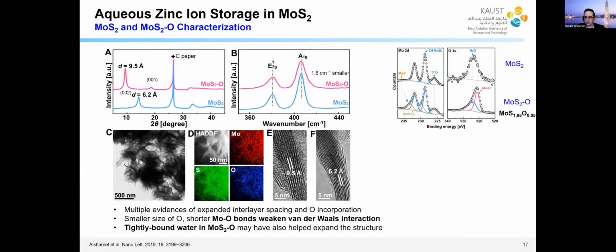Another thing is that you can also look at the XPS. Okay, we looked at the orbitals of Mo 3d and oxygen 1s. On top here is the molysulfide, on the bottom is the molysulfide oxygen, and you can see this molybdenum-oxygen bonding evolving with the oxygen substitution. You can calculate the exact composition after the hydrothermal synthesis, and we find we have this composition, 1.95 of sulfur and 0.05 of oxygen. There's another factor actually, it turns out, besides the oxygen: potentially crystal water.